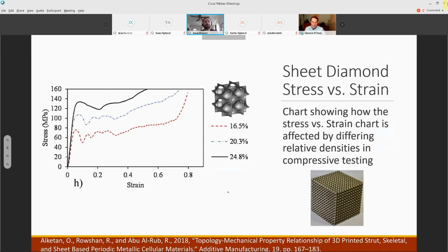So here is a stress strain curve for differing densities for the sheet diamond structure at 25%, 20%, and 16%. You can see that for each, it's about a 5% jump in density. You get about a 25% gain in the peak stress, and about the same in the strain area as well. So you get a lot of gain. We saw it between 10 and 25%, a lot of strength gain, and we still get it in between these different nominal notches.